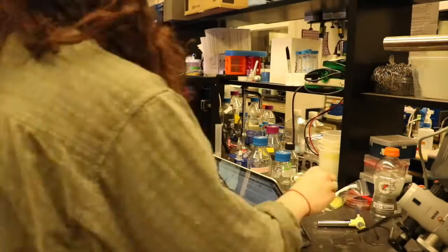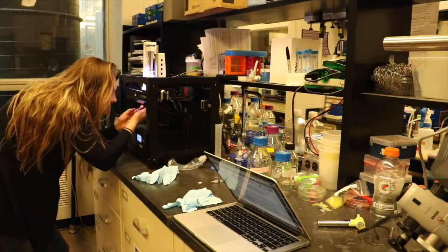Once we found these settings, we were able to print samples to be tested on the rheometer to find the material properties. So our project for the 3D bioprinter was definitely a success. We've been able to totally redesign the nozzle so that it can print different biological materials. And we were able to successfully cure 5 layers to each other seamlessly. So that was really like a benchmark for this.